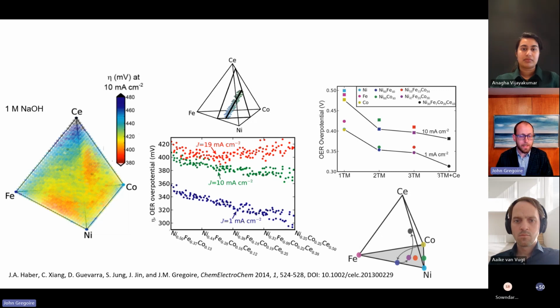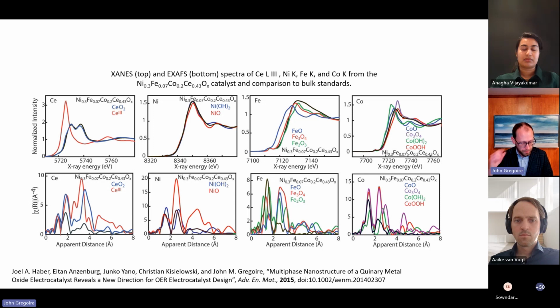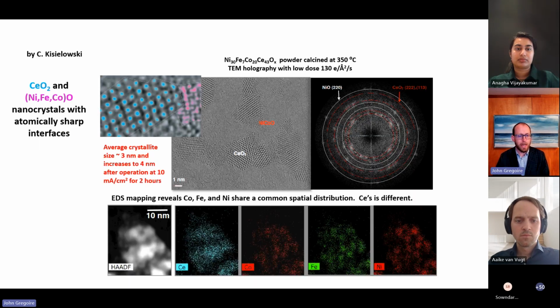So why is this? We tackled this for a number of years with a number of collaborators. It's a wealth of data, which I'm not going to go through in detail, but I'll talk you through some of the high-level results. The first one was understanding the transition metal oxidation states and local coordination via X-ray spectroscopy with Junko Yano's group. We used this to generalize some observations that we got from collaboration with Christian Kisielowski on atomic resolution TEM, which was an incredibly difficult measurement because these were very radiation sensitive materials.